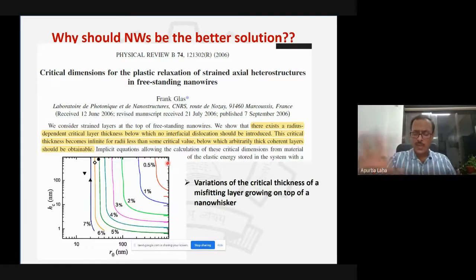Now, there are other benefits of the nanowire. One of the benefits is to have defect-free structures, as we saw. There is a fundamental study showing that the critical thickness between the two layers becomes very high if you shrink your radius. So that's one of the advantages you can get here. And there's another big challenge, which is doping. If you look at the large band gap material, aluminum nitride, the dopant level is far away from the band edges, so the doping activation energy is super high. This is a planar structure I'm talking about.